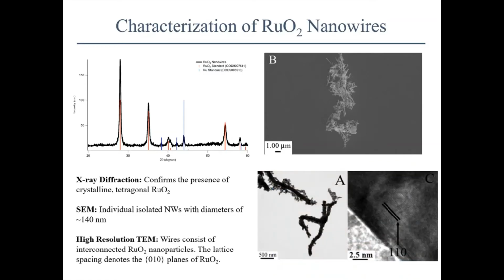And then we did high-resolution TEM to measure the crystalline structure of the wires. As expected, because of the sol-gel chemistry, we saw that these were polycrystalline, meaning they were composed of multiple interconnected ruthenium oxide nanoparticles. This is pretty typical for sol-gel chemistry; it leads to polycrystalline materials. And we could look at the lattice spacings to see that this was consistent with tetragonal RuO2. The lattice spacings could be indexed to the lattice spacings of ruthenium oxide.